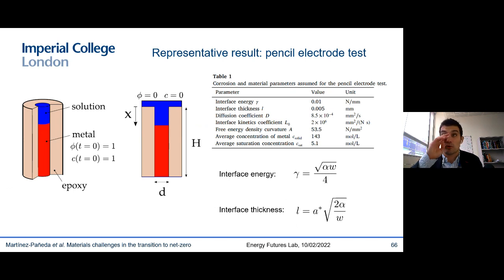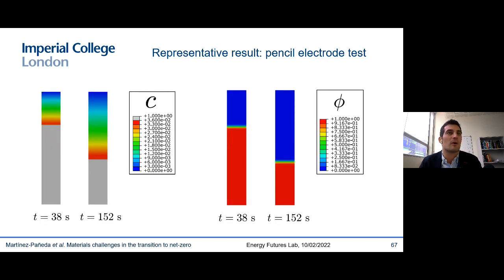And let me just show some examples of what we can predict. This is a classic benchmark test known as the pencil electrode test. The problem is essentially one-dimensional. What you expect to see is this metallic bar corroding uniformly, and there are both experimental and analytical solutions for the case of diffusion control corrosion. You can see here some representative results. On the right is the evolution of the corrosion front, as given by the phase field, and on the left is the distribution of metal ions.